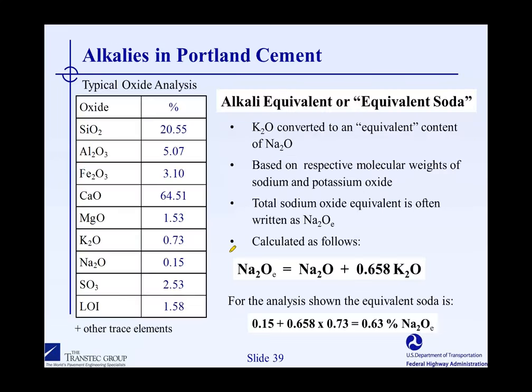my computer's running a bit slow, is calculated by taking the sodium oxide content of a cement and adding to it 0.658 times the potassium oxide content. And that 0.658 is not just a fudge factor, that is actually based on the molecular ratio of sodium oxide to potassium oxide. What that actually means is a pound of potassium oxide will contribute to ASR roughly the same as 0.658 pounds of sodium oxide. So we use that equation to come up with our sodium oxide equivalent.